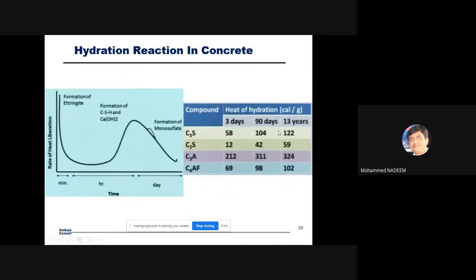Hydration, we earlier also discussed. Though we have these components, tricalcium silicate, dicalcium silicate, it liberates a lot of heat into the concrete. If you see 90 days, 104 calories per gram of cement. More liberation comes from tricalcium silicate, and tricalcium aluminate also liberates a lot of heat initially. That's why this is also being restricted. Of course, in terms of percentage, it is only 7 to 8%. So the major heat generated in cement is from tricalcium silicate. Later C3A, C4AF also, but again the percentage is quite low, and then C2S.